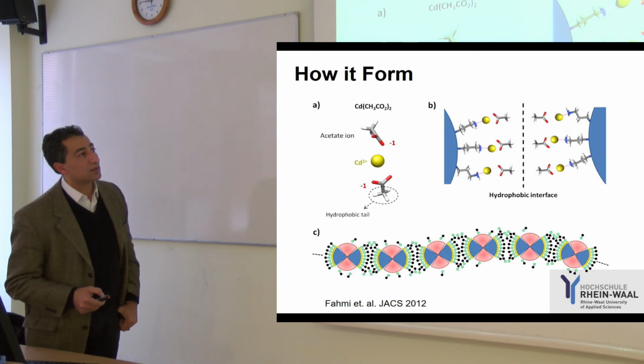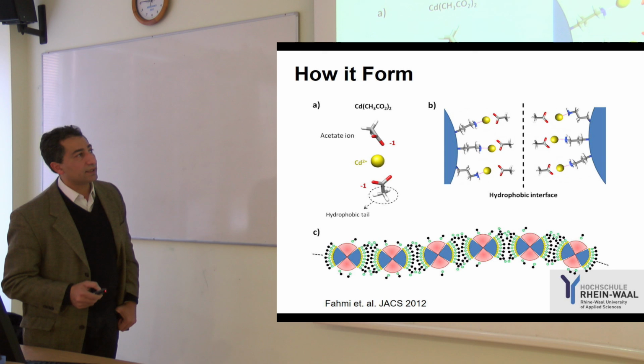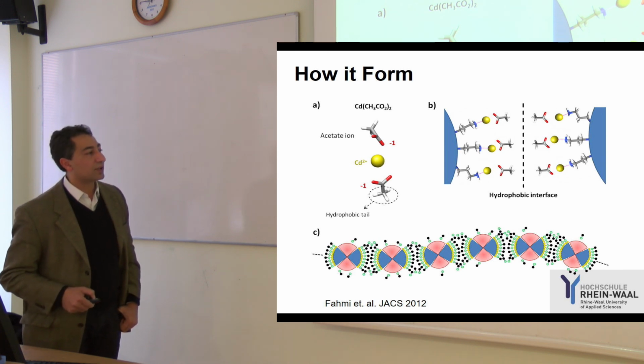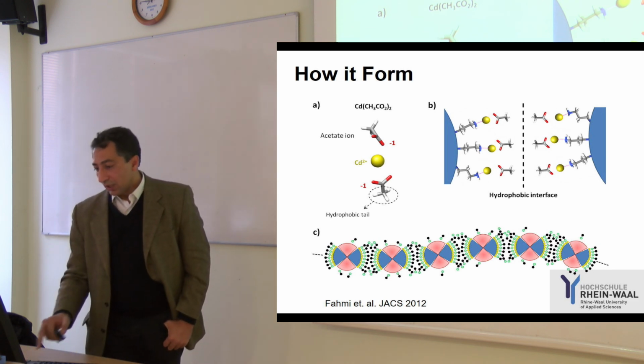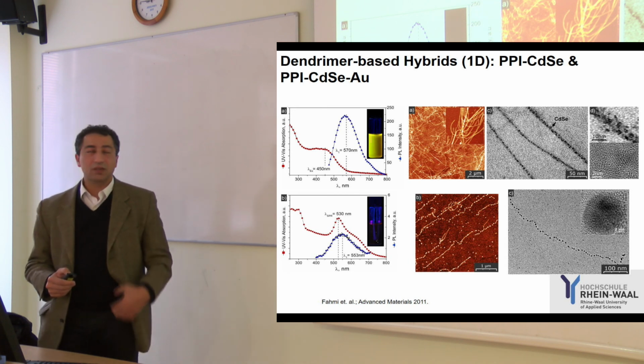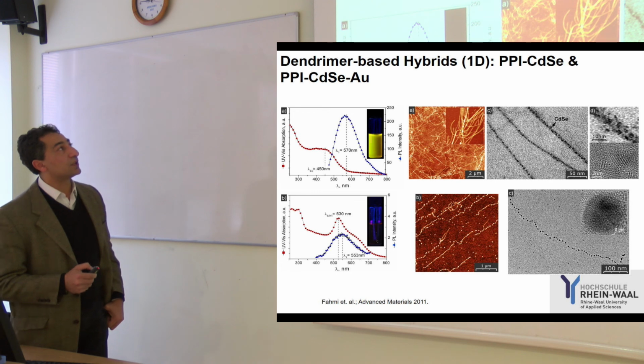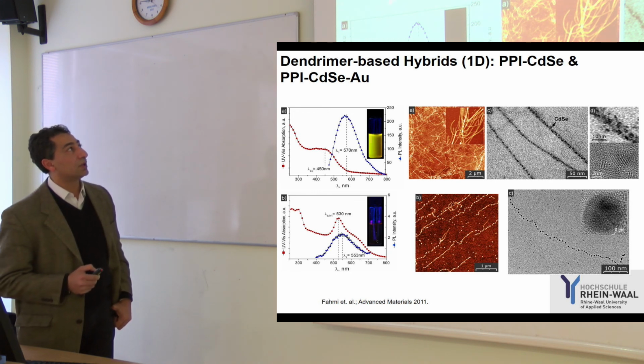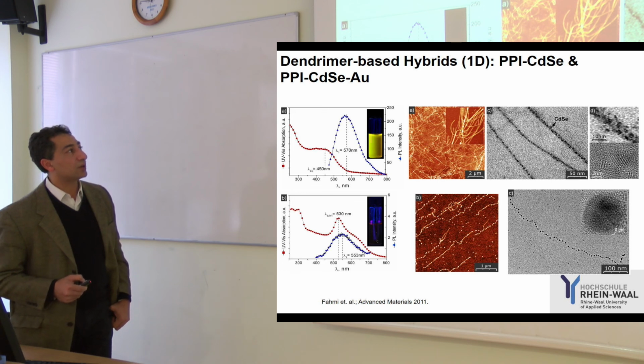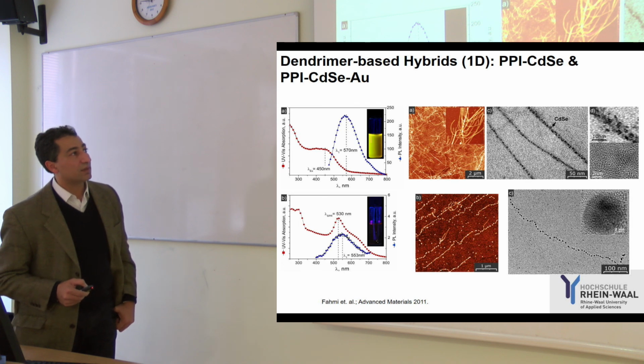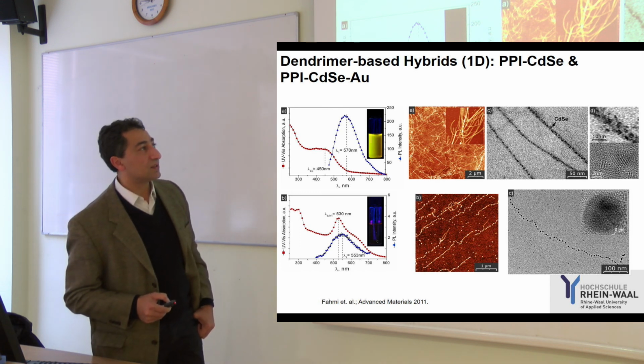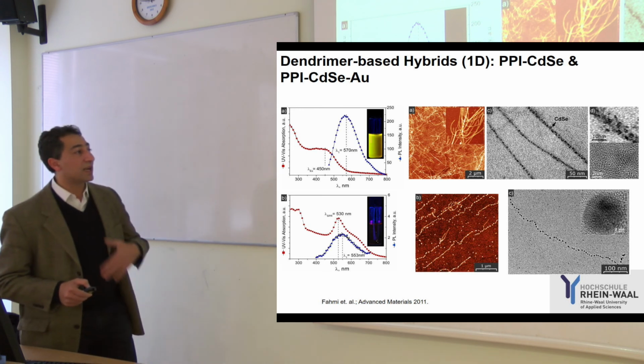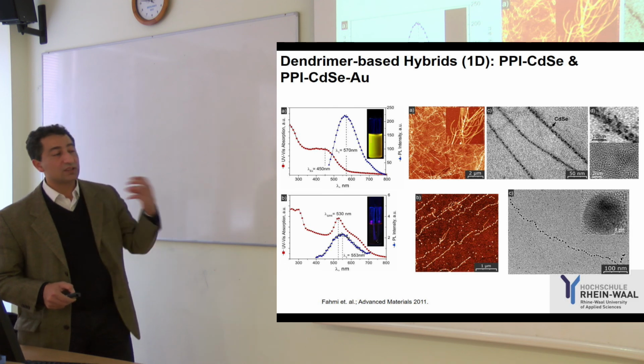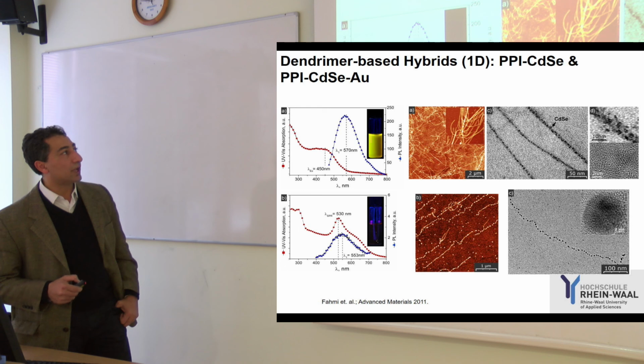We found that the different levels of inorganic can work in between the two dendritic structures, so that we can have a very long fiber, as I showed you. As I mentioned, there was a reason why we're using cadmium. Cadmium is a very nice material that can be used as a precursor to make semiconductor nanoparticles. In this case, we use cadmium as part of cadmium selenide to make this inorganic nanoparticle. You can see the fluorescence is very nice, with a very high aspect nanofiber based on semiconductor nanoparticles. We did exactly the same: we use this semiconductor nanoparticle as a scaffold to add another kind of metallic structure, so that we have metallic and semiconductor together. And as you see, as in the semiconductors before, we have a very nice fluorescence.